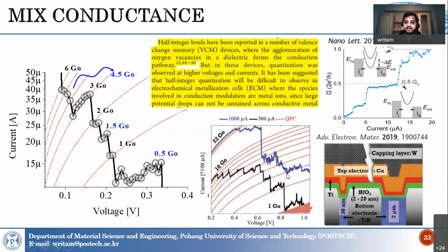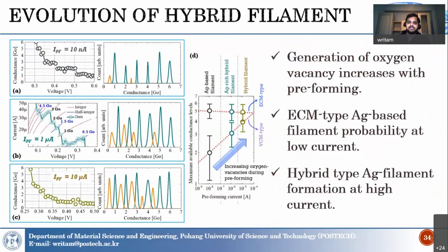However, this kind of data is very difficult to achieve, but it is possible to get those kinds of references for a pure metallic filament. Once you have a mixed filament, or some impact of oxygen vacancies, you can have multiple intermediate steps. So in this case, when we operate the devices in the 10 nanoampere range, you can see a very clear scanning, like 6, 5, 4, something like that.